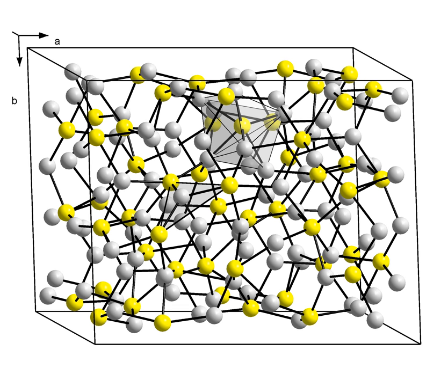There is also a crystallographically distinct phase, the mineral djurleite, with stoichiometry Cu1.96S, which is non-stoichiometric, with a range of Cu1.934S to Cu1.965S, and has a monoclinic structure with 248 copper and 128 sulfur atoms in the unit cell. Cu2S and Cu1.96S are similar in appearance and hard to distinguish one from another.